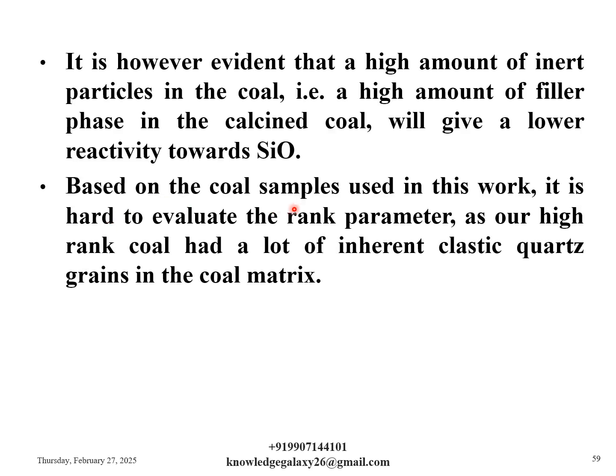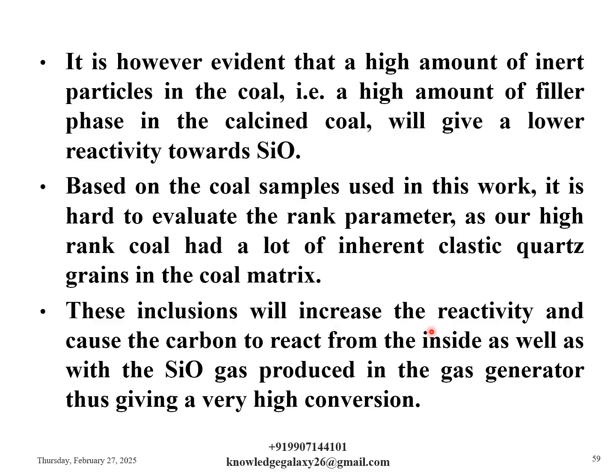Based on the coal samples used in this work, it is hard to evaluate the rank parameter, as our high rank coal had a lot of inherent clastic quartz grains in the coal matrix. These inclusions will increase the reactivity and cause the carbon to react from the inside as well as with the SiO gas produced in the gas generator, thus giving a very high conversion.